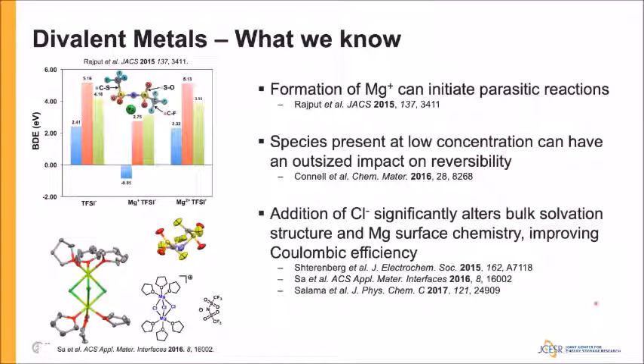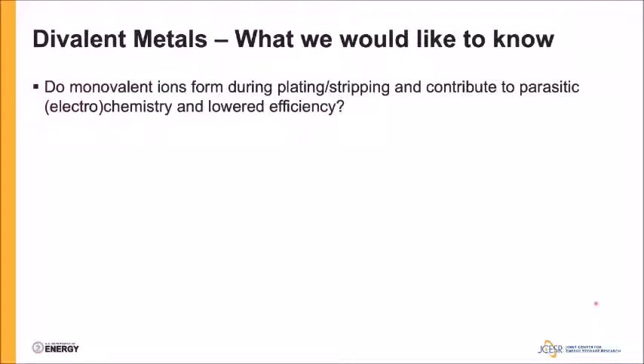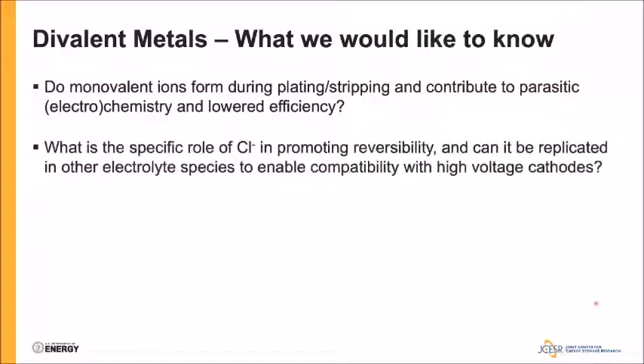And finally, as the last speaker pointed out very nicely, the addition of chloride to a lot of electrolytes can significantly alter solvation structure and magnesium surface chemistry, in a lot of cases leading to improvements in coulombic efficiency. Now, with all this insight, there's still a lot of questions we'd like to answer. In particular, there's been a lot of theoretical evidence that monovalent ions form, but thus far we haven't been able to show experimentally that they're actually present. So we'd like to know, do these monovalent ions form and contribute to parasitic electrochemistry, resulting in lower efficiency? In addition, what's the specific role of chloride in promoting reversibility in these systems?